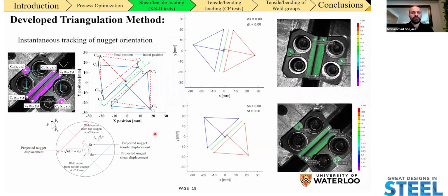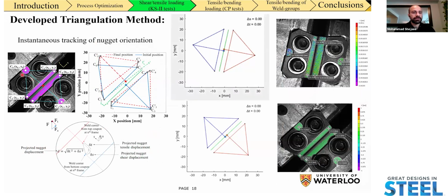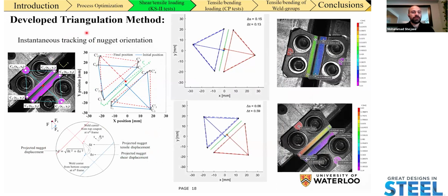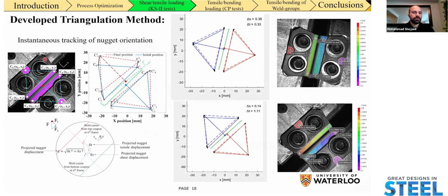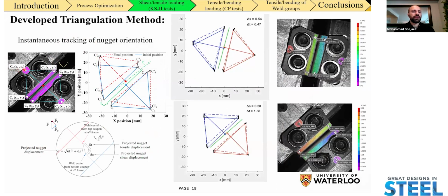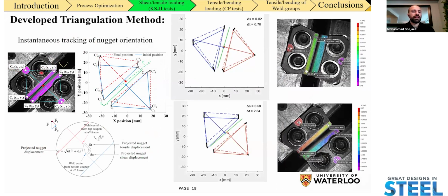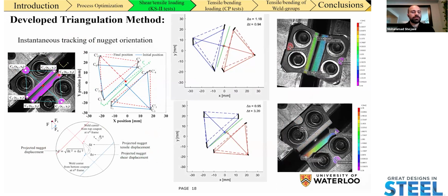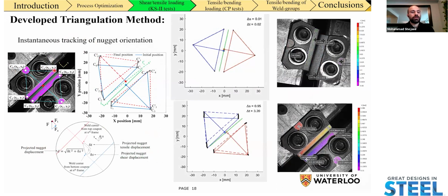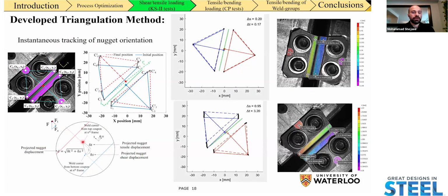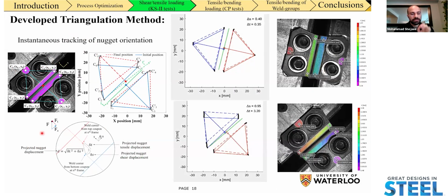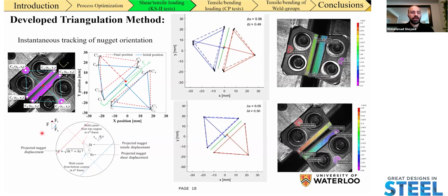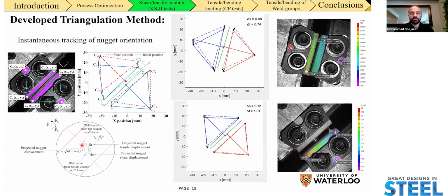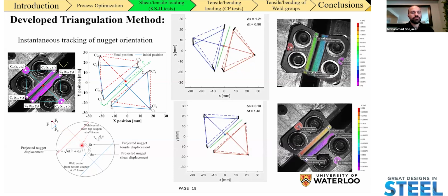Now, in order to do that, we developed this methodology that we're referring to as the triangulation method. What this method essentially does is that it tracks the instantaneous orientation of the nugget from the beginning of the test to the end of the test. The way that it does that is we're using circular inspectors from the DIC in post-analysis and constructing one triangle on each KS2 coupon half. And by approximating the projected nugget center point from each coupon half, we are able to track the displacement that we have from each coupon half throughout the whole test.